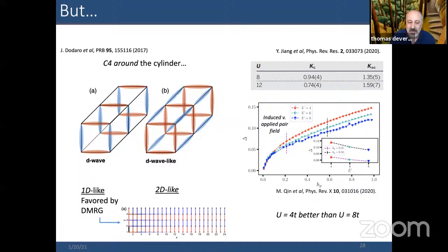So I've shown you that the order parameter, or the correlations, change sign under a rotation of 90 degrees within the cylinder, but you can ask, well, what about C4 symmetry going around the cylinder, meaning wrapping around the cylinder, which is what A and B show. And what we find is that DMRG favors this more one-dimensional flavor of true D-wave going around the cylinder. It fits perfectly, actually, that it's a plus minus going around the outside of the cylinder, which is not what you would like to see in the 2D case.